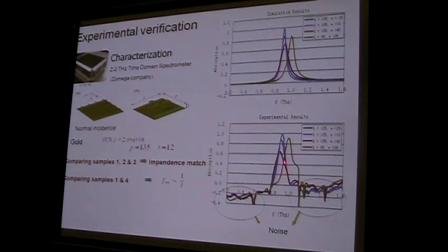All these things are consistent very well, and the absorption efficiency is very high. This is simulation, and this is the experimental result. You see they are consistent very well. And this is the material spacer. We're just using a standard polymer, SU8, and we made this absorber, and it works well.